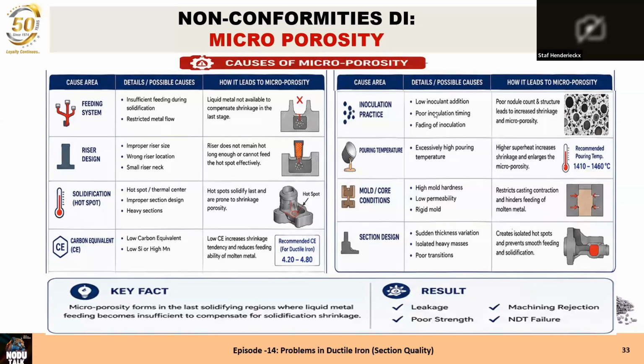The hotspot is the last solidifying metal. Let's say there you first have micro shrinkage, and if the hotspot is really not compensated by the riser, then it becomes a macro porosity. So in a hotspot, micro is the start of a porosity later. The carbon equivalent, of course: low carbon equivalent increases the shrinkage tendency and reduces the feeding ability of molten metal. For sure, never forget that the nodule count is very, very important.